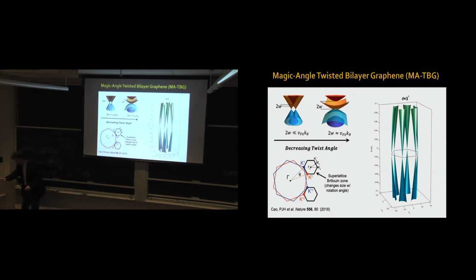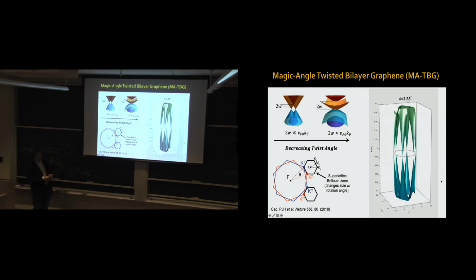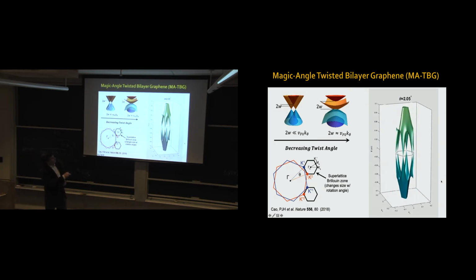So I'm going to run a video. There, you see the electronic structure evolving with angle. A set of bands appears, isolated via band gaps from the next set of bands. At 1.1 degree, this becomes very flat there. And then it continues to evolve in a complex manner.